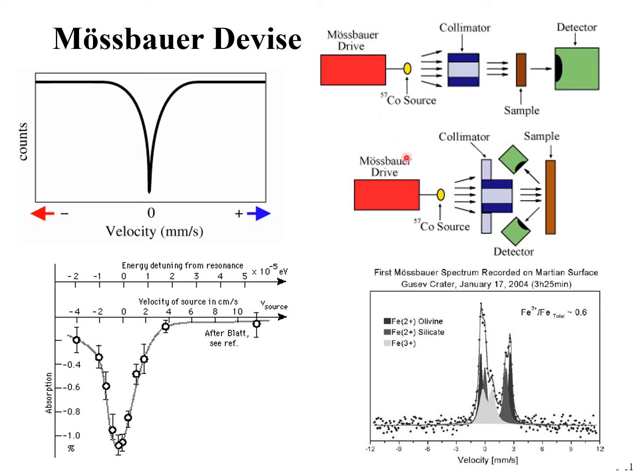Here's another source, an example where Moessbauer spectroscopy is done on iron, where another collimator, a sample, the sample could be a surface, and detectors are off at angles. So again, you should see scatter. A decrease in scatter as a function of this vibration would mean that some of the photons have been absorbed by the materials. This was used on the Martian surface. The data is shown here.